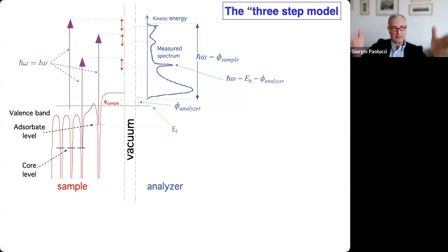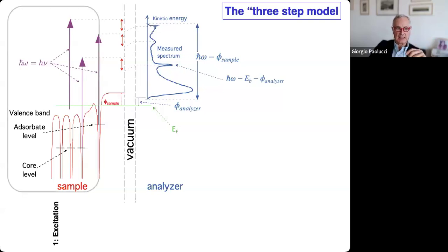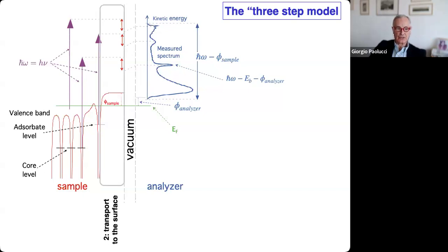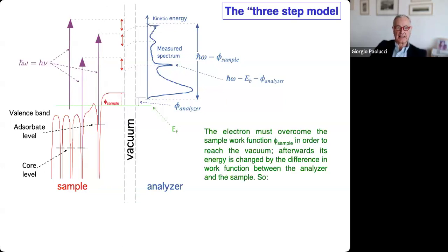And basically, you move these electrons, which are occupying states below the Fermi level. You kick them out. They go through a potential barrier due to differences in the work function, and then they enter into something that looks at the kinetic energy. So first you excite them, then they are transported to the surface, and then they go through the vacuum, and then they go into the analyzer.